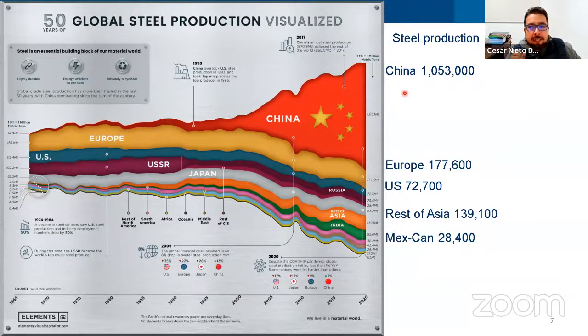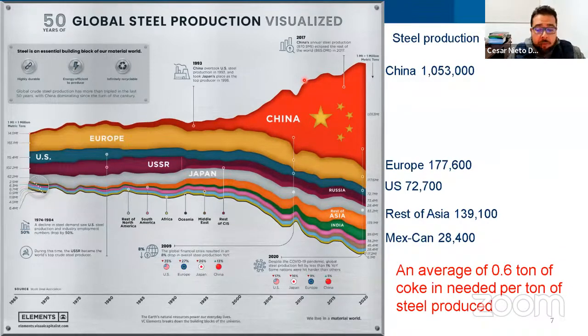Around the world, the biggest producer of iron is China, with around 1 million tons per year of steel, followed by Europe, the rest of Asia. Japan produces a lot of iron too. Mexico also produces some iron together with Canada, and you see it's a very demanded product. Now, on average, to produce 1 ton of steel, it depends on the processing, it depends on the production line, but you need around 0.6 tons of coke. 600 kilograms of coke is needed to produce 1 ton of steel.